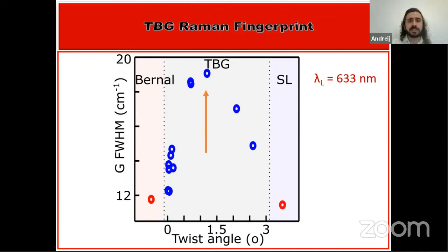Okay. And interestingly, this maximum value is close to 1.1 degrees, which is the magic angle. So it may tell us that the electron-phonon coupling related to the G width is stronger for magic angle twisted bilayer graphene. So we are trying to investigate this further, and we believe we are going to get nice results on this topic.